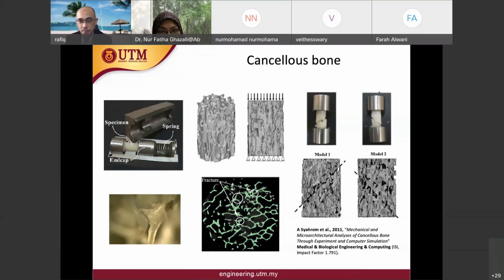You can see that the pictures above are of the broken cancellous bone, and underneath, the two models are the finite element models of the cancellous bone. I believe that we got the model from micro CT scan at one of the agencies, Agency Nuclear Malaysia, which has this micro CT scan equipment. We brought our cancellous bone specimens, scanned them using that micro CT, and that's how we got this cancellous structure, the finite element model.